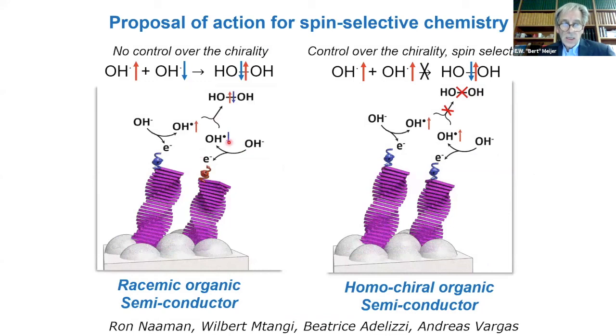The proposal is that if you have a racemic semiconductor and you tunnel electrons through, you make OH radicals of spin up and spin down. That gives you the possibility to make a singlet pair, making hydrogen peroxide. However, if you have a homochiral organic semiconductor, you only make OH radicals with spin up or spin down. And as a result, it is impossible to make hydrogen peroxide, meaning that the OH radical reacts further to hydrogen and oxygen. This obviously needs much more work, and certainly to make these substrates more stable.